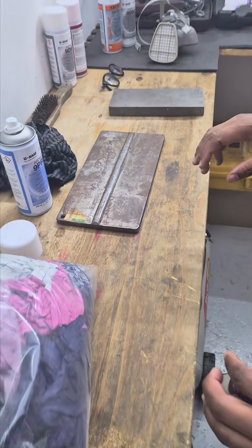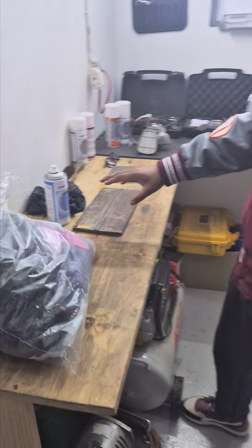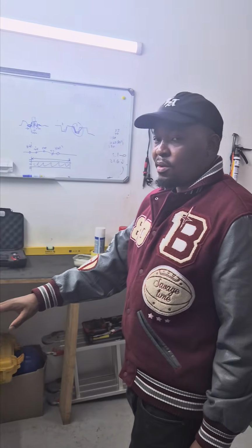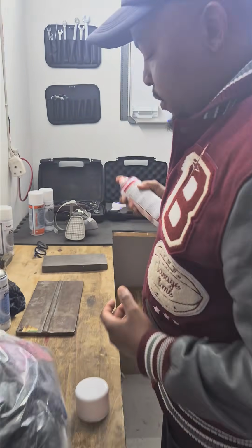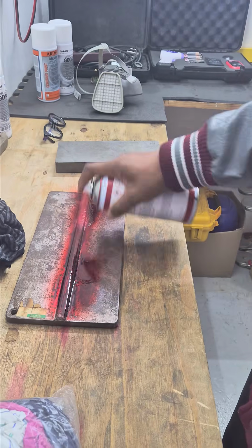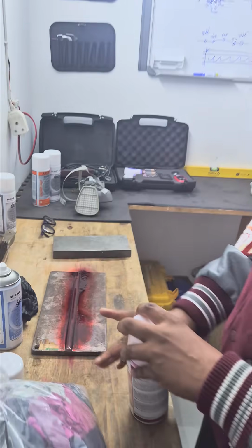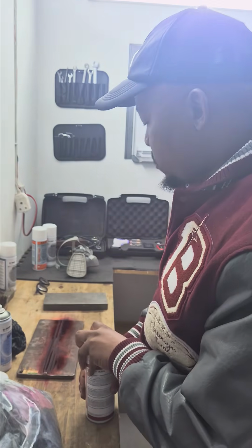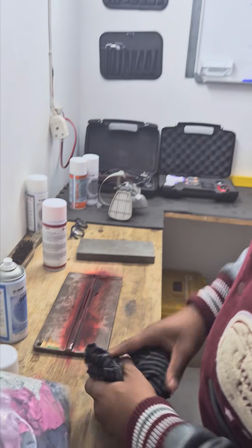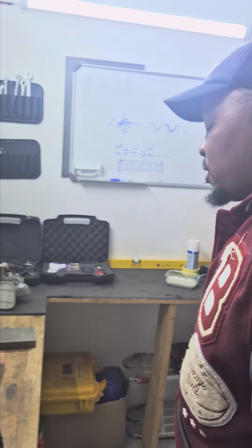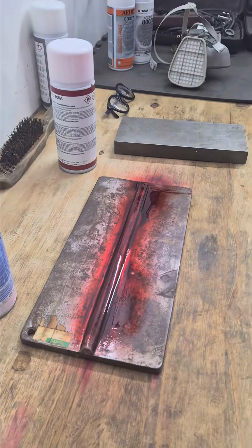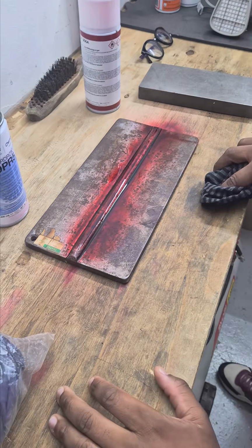All right, so it's very imperative that you clean your sample thoroughly. Solvent removable penetrant on the surface. So usually if you're testing a weld like I am, you'd be required to cover the weld in the heat affected zone. So the thing about penetrant is you are required a dwell time of about 15-20 minutes. So we allowed a 20-minute dwell time.